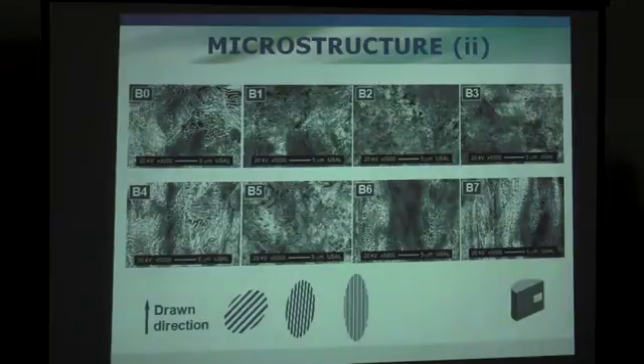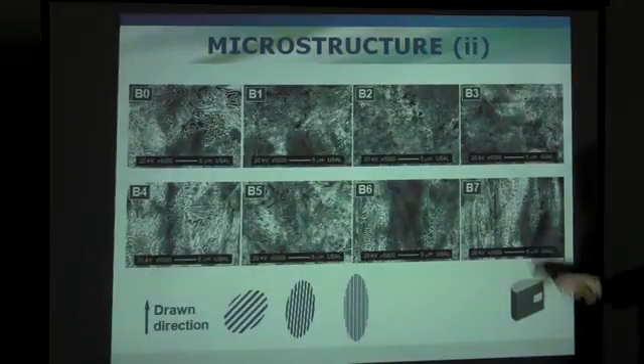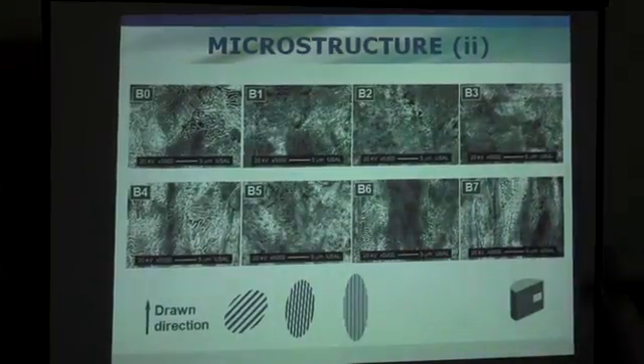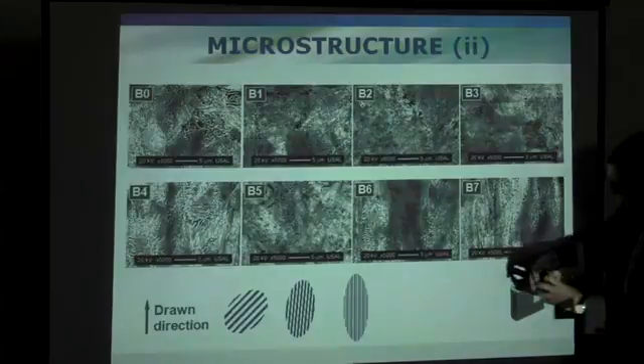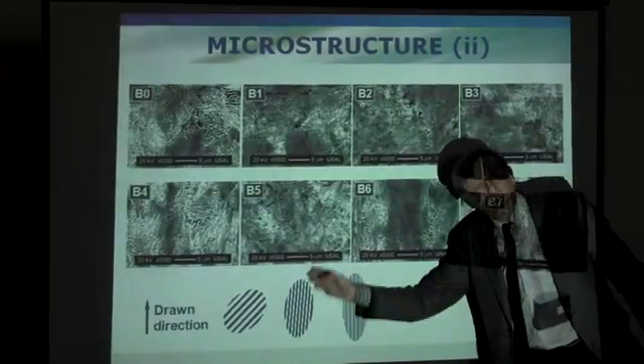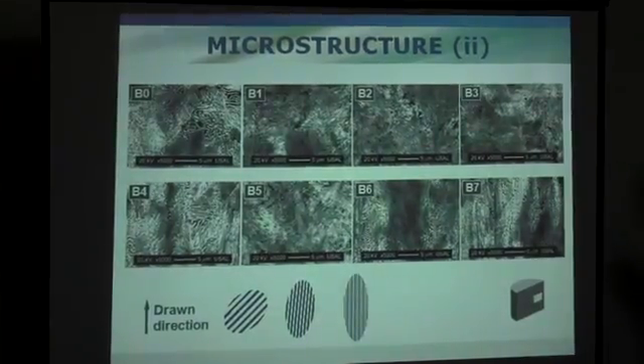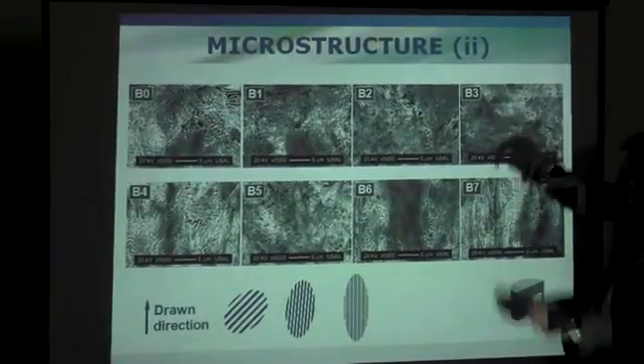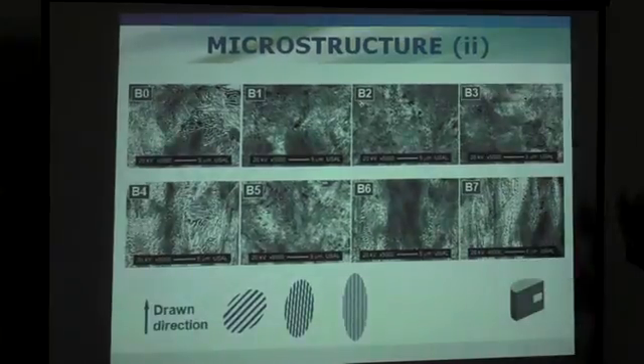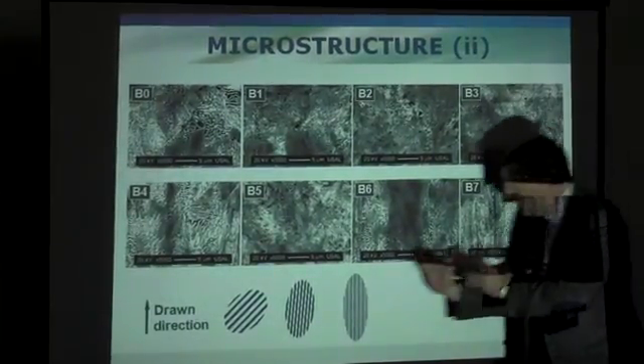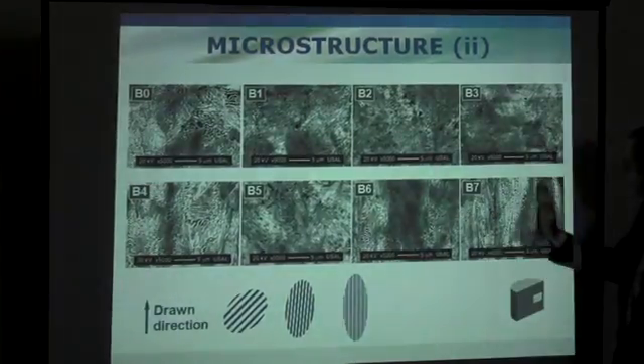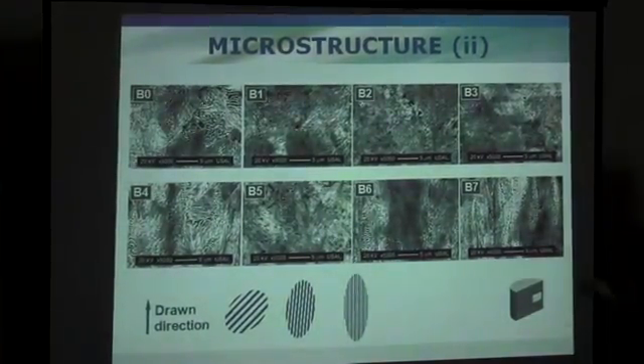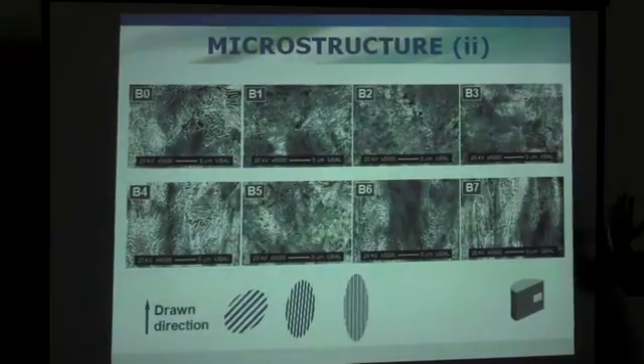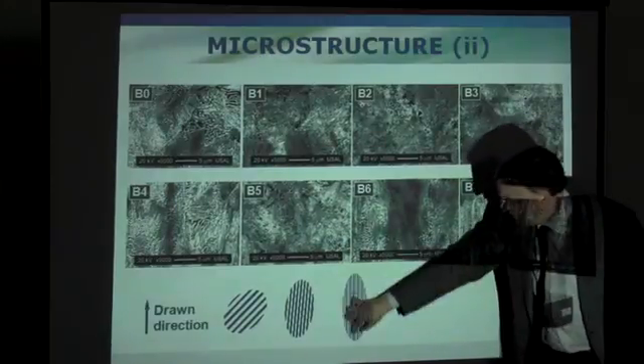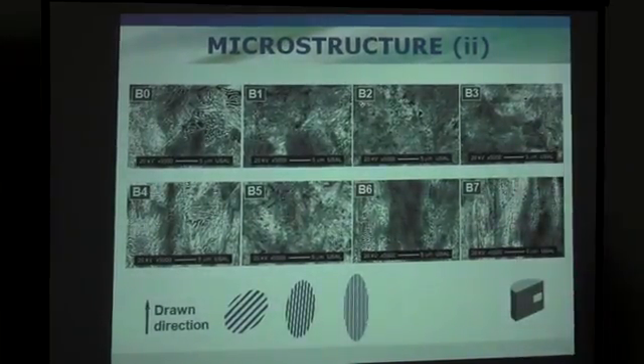This is a microstructure like a composite material, heavily drawn, and we have a clear progressive geometrical evolution of the two microstructural levels, both pearlitic colonies and pearlitic ferrite-cementite lamella. We have a progressive orientation of the colonies, and progressive slenderizing. They become more slender in the drawing direction, and the lamellae also are progressively oriented quasi-parallel to the drawing direction, or y-axis, in the final stages of drawing, and there is a decrease of pearlite interlamellar spacing, which means an increase of packing closeness, as in the case of the transverse section.